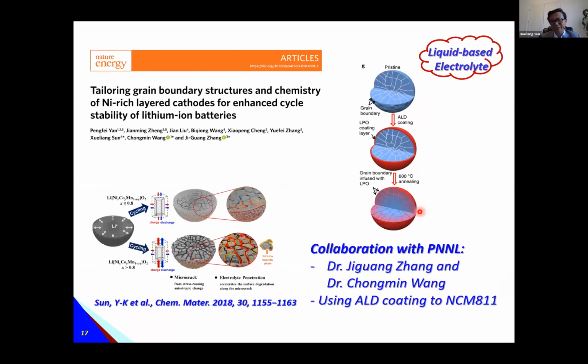So here, in collaboration with PNNL, Dr. Zhang's group and Dr. Wang's group, we try to understand the interface in the liquid electrolyte system. We know that high-nickel cathodes have cracks, particularly along the grain boundary. So the motivation for our study, we tried using ALD coating. And after coating, we do annealing to try to send the coating material into the grain boundary